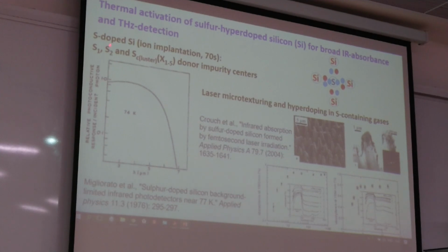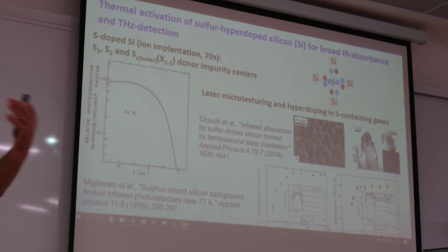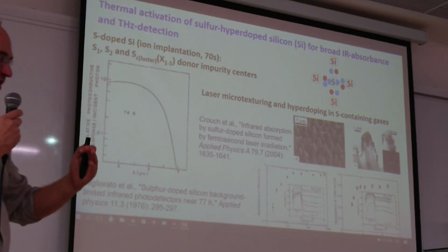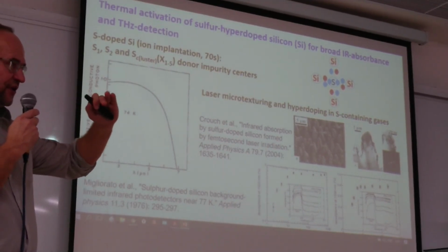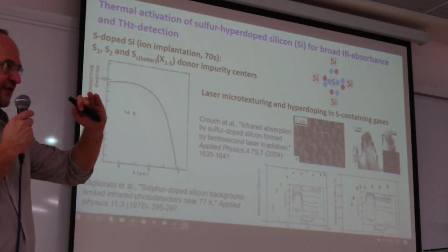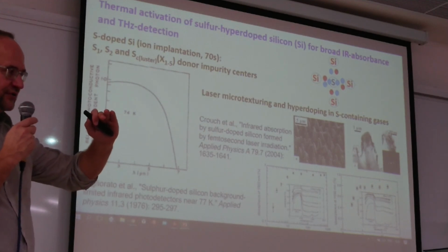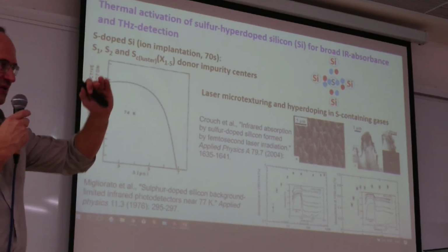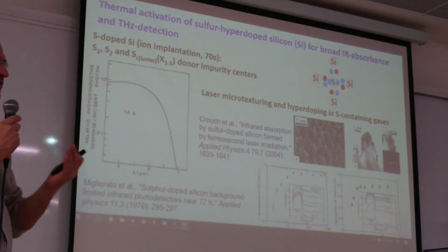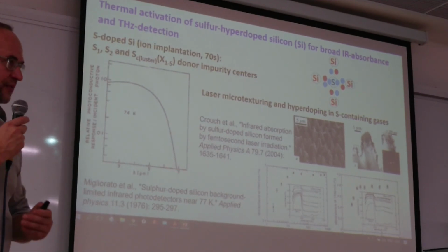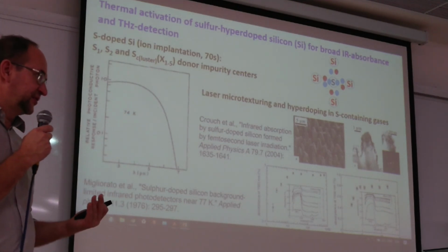because of their band gap. But if we introduce these sulfur impurities into its structure, sulfur, as you remember, donor impurities occupy positions close to the conduction band, and small infrared photons can promote electrons from sulfur to the conduction band. So there is a photoconductivity response of hyperdoped silicon. And in the 70s it was observed that photoconductivity in such materials can occur up to 7 micrometers. So silicon becomes a very interesting material because of this technology.